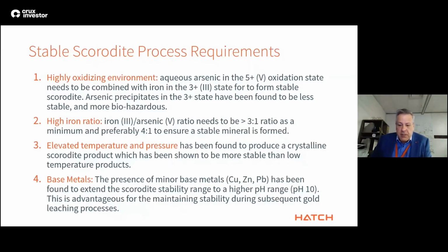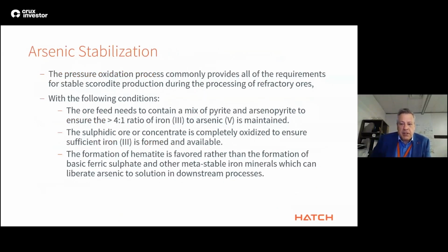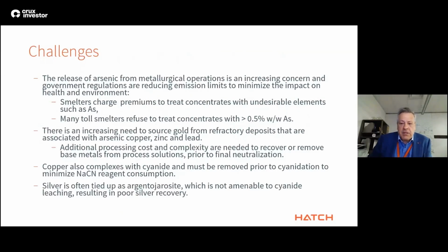The presence of base metals such as copper, zinc, and lead extends the stability range of scorodite to higher pH range, to pH 10, which is desirable for maintaining stability during subsequent gold leaching processes. Pressure oxidation inherently stabilizes arsenic by providing all of the requirements for production of stable scorodite from processing of arsenical refractory gold ores. The release of arsenic from metallurgical operations is an increasing concern. Government regulations are reducing emission limits to minimize the health and environmental impact. More and more gold is expected to be sourced from refractory sulfide deposits, having a high association with arsenic, which poses additional processing challenges.